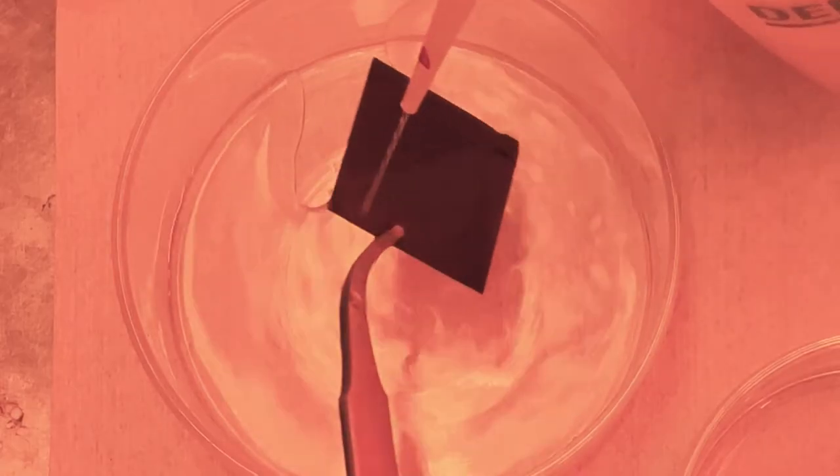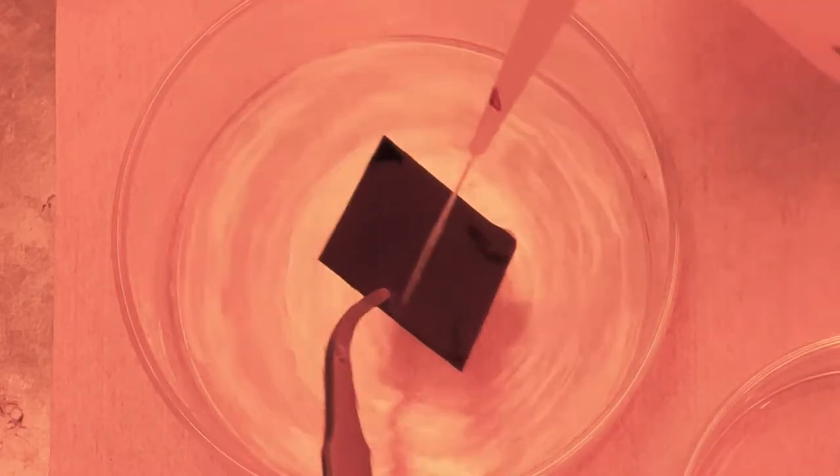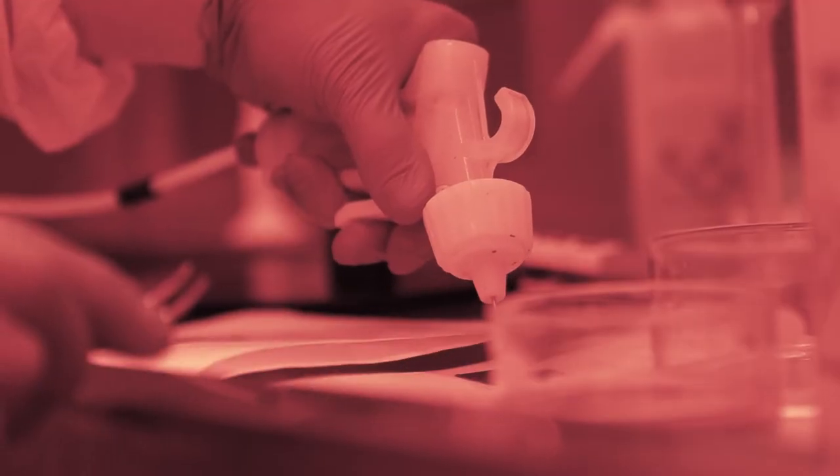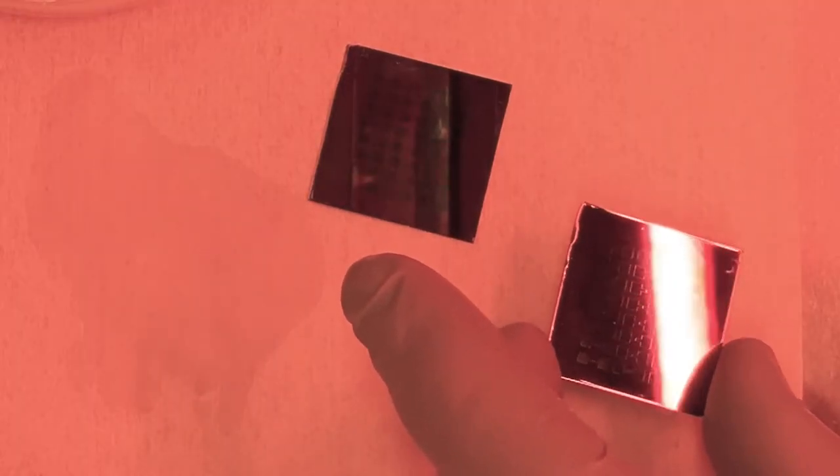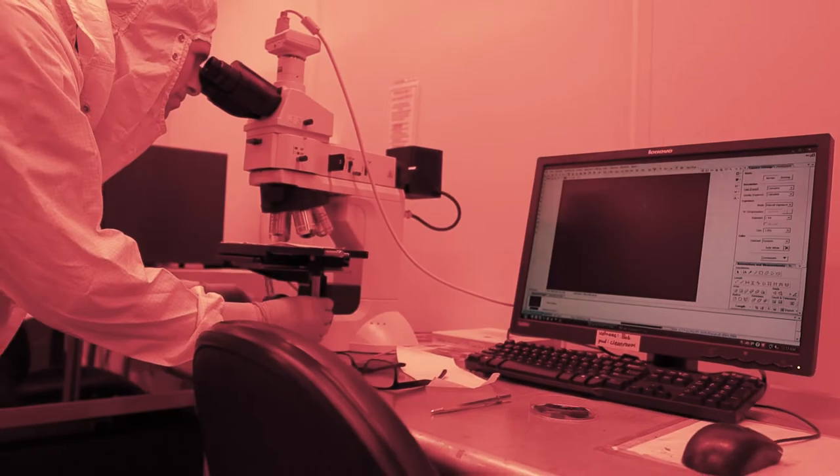You know, a few extra minutes is not a big deal. We're working with features that are on the order of hundreds of microns. So you have a pretty wide window. If we're doing sub-micron features, we'd want to be really precise with development time. Looks good.